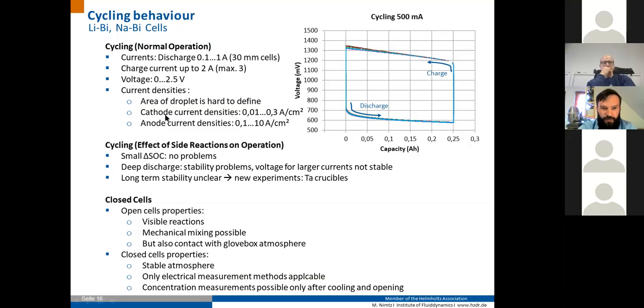But related to the cathode current, to the cathode surface, we had current densities of around 0.01 to 0.3 ampere per square centimeter for typical discharge of the cells. The anode current densities are much higher depending on how you define the surface, up to 10 ampere per square centimeter.